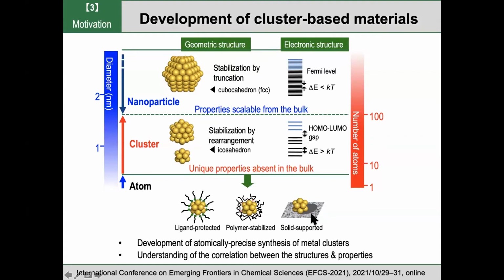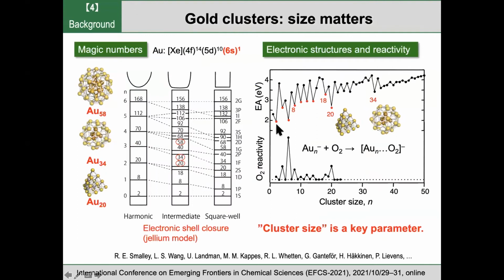We focused on gold clusters because so much fundamental knowledge has been accumulated for this system by using molecular beam techniques. We know that gold clusters with sizes of 20, 34, 58 are very stable. We call these numbers magic numbers. If you solve the Schrödinger equation by assuming this kind of potential, which is between harmonic and square well potential in the quantum chemistry textbook, you have these discrete orbitals. If you fill the orbitals with these numbers of electrons, you can close the electronic shell. Because these numbers and these magic sizes are the same, we can say that the stability of gold clusters is explained by the closure of the electronic shell.